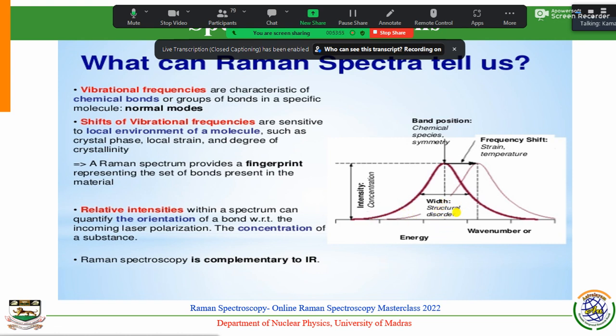Not only that, the frequency shift also tells the carrier concentration, especially the localized carrier concentration you can identify. Even Hall effect measurement can't identify the localized value because it gives only a bulk value for some kind of area, but at the particular laser spot level you can identify the carrier concentration by the shift of that particular frequency, right? But which frequency, which mode you have to choose, that's important. And the Raman spectroscopy must be confocal in nature, so that we can identify it very easily.